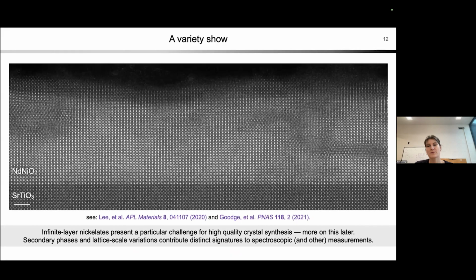And it's not so surprising that the first sort of batches that came out, although they showed superconductivity, when we do a STEM image and we go in and we look at these materials, you can see that it's not exactly what we would consider a perfect lattice, right? And so there's a lot going on, but you can see from the STEM image that in this sort of green box, there are regions which look basically like we think they should look. So they look very high quality.